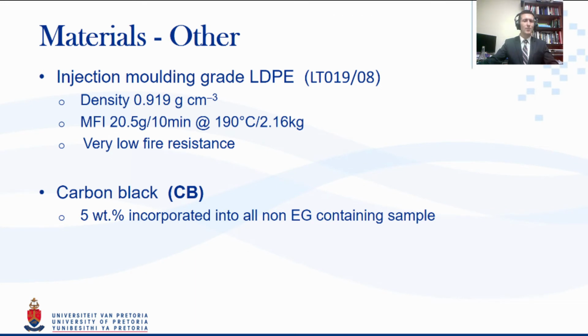The next slide is which materials we used in terms of the carbon black and the injection molding grade LDPE. But what's of key interest here is that this injection molding grade LDPE is an exceptionally low fire resistant material. This actually burns a lot more readily than most LDPEs, and when it's exposed, for instance, to cone calorimetry, there is very quick and even pyrolysis of the entire material.